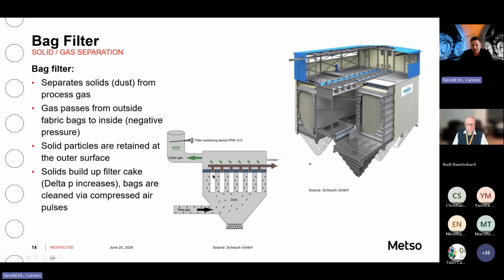So you can imagine material accumulates on the outside of these filter cloths, and therefore it's getting more difficult to suck the air through, which you can measure by a change in the pressure drop. And then there's an automated cleaning device that cleans the bags. So this is the way how we can de-dust the material out of the gas stream. The dust emissions in modern baghouses are below 10 milligrams per cubic meter. If it should be required, we can also reduce that to 5 milligrams.